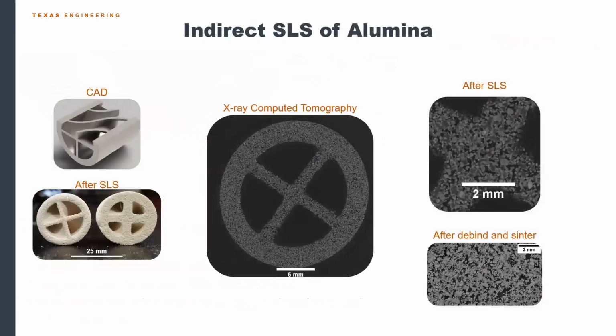As I mentioned, with the indirect SLS process we're able to tune the porosity. Porosity can be beneficial for some applications, especially on the surface. An example application would be catalysis, where you want the surface of the solid to interact with some liquid or gas. In the indirect SLS process, we're able to tune that small-scale porosity on the surface, which I'm showing with X-ray computed tomography images. You can see there's some porosity down at the particle scale, on the order of microns.